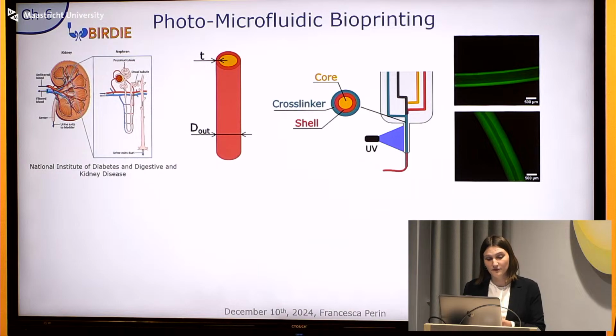And the next step forward that we did is that, due to preliminary experiments from the Birdie project showing the cells suffering a little bit when printing with alginate and ions, we decided to try and print just with photocrosslinking. And this was achieved and was optimized by a design of experiment approach in which we studied how the different printing parameters had an effect on the outer diameter and the thickness of the fibers that we could produce. Here you can see two examples of fibers that were made fluorescent, and you can see that they have more or less the same outer diameter, but they have a very different lumen.